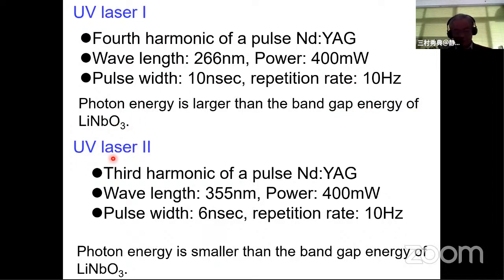And the second one is the third harmonic of a pulsed Nd:YAG laser. The wavelength was 355 nanometers. The power was 400 milliwatts. The pulse width was 6 nanoseconds. The repetition rate was 10 Hz. In this case, the photon energy is smaller than the bandgap energy of the lithium niobate crystal.